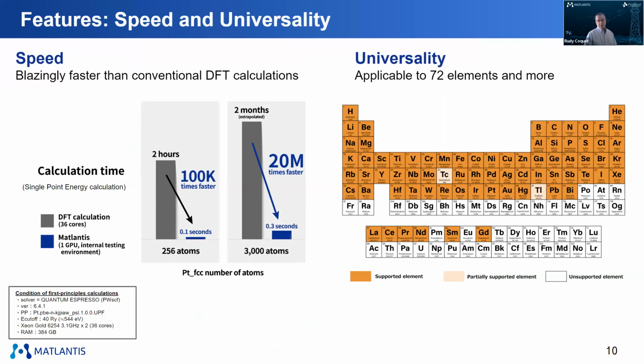The main features are speed and universality. So speed, first of all, because if you compare to DFT, we have done, of course, several comparisons, but you can actually take a very simple platinum face-centered cubic cell of 256 atoms. DFT will take you about 2 hours with the conditions that we have listed here at the bottom of the screen, and Matlantis would take a fraction of a second.